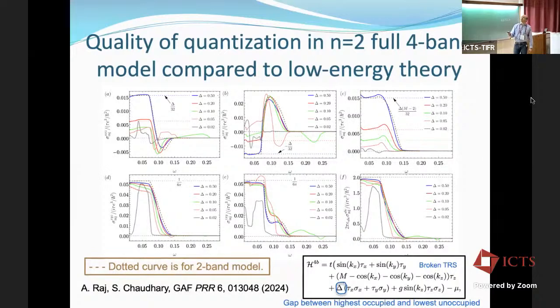So the second message here is that if you have more than just the two bands, it makes a big difference. So having a four-band model instead of a two-band model, where the four-band model has the same low energy theory around the Weyl points, actually completely destroys the quantization. So there's a parameter here, delta, which is telling you how separated the two low energy bands are from the two higher energy bands. And the bigger delta is, the closer you get to quantization, but you still remain away from it. So having just an extra pair of bands away from those low energy bands basically destroys the quantization. So even in the absence of interaction effects or disorder effects, you already don't expect to have quantized response in the system. That quantization is a strict artifact of that low energy theory of just two bands.